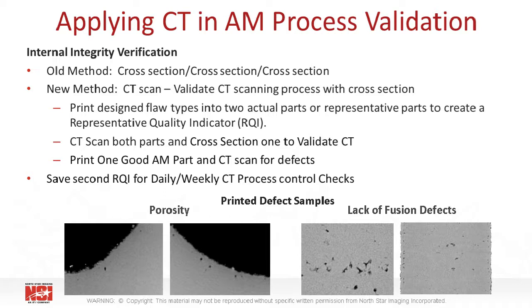One of the 2 defective parts should be cross-sectioned to validate the CT findings and confirm the size of the actual printed defects, and that other defects are not present that are missed by CT. The other can be used for performing process control checks on a daily or weekly basis. And once the confidence is gained in the full detectability through CT for similar applications, it may be possible to eliminate the cross-sectioning of the second part.